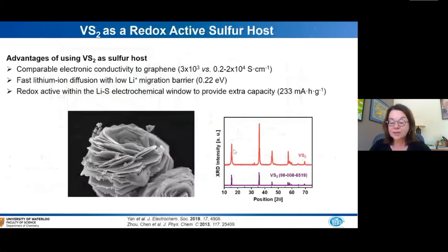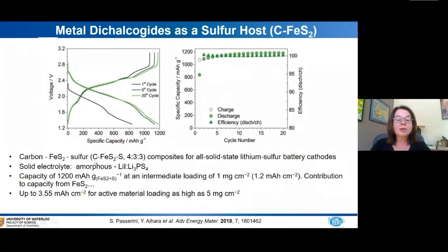Their composites were prepared with a combination of carbon, iron disulfide, and sulfur in a 4:3:3 ratio, so they have a low sulfur content.